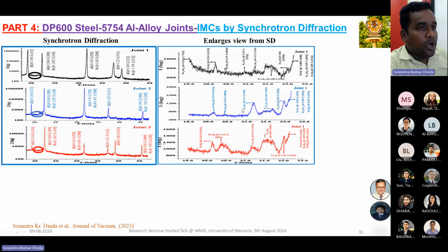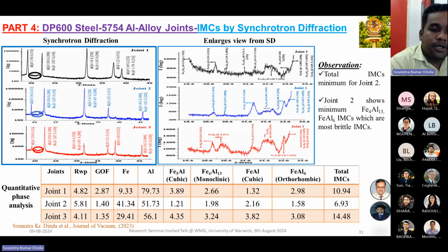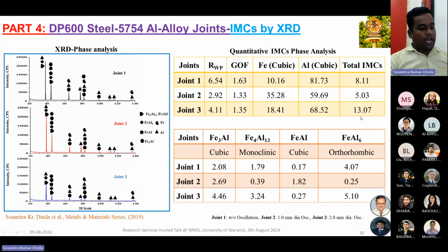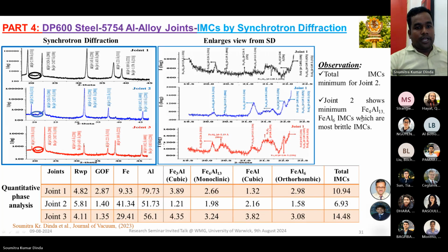and we got the intermetallic peaks individually. Then again we did the Rietveld study, and we found that the same four types of intermetallics are present, but the percentage values are a little different. In previous cases you can say 8, 5, and 13; here we got 10, 7, and 14. So it's close, but we assume that because synchrotron diffraction scans a very small region, it gives a more accurate result, showing the individual intermetallic peaks.